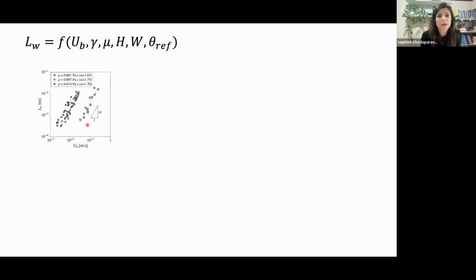Okay, so let's start with the speed of the bubble. As expected, if you increase the speed of the bubble, this is the wetted zone. At least for the first graph, I explained this. On the Y axis, you always have the wetted zone. At this point, it's still dimensional. And then I'm measuring the wetted zone versus the speed of the bubble. And you see that the curves are shifted. This is a log-log plot, so they're always some sort of a power law, but they're shifted.